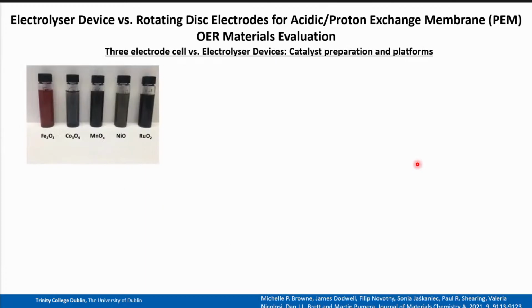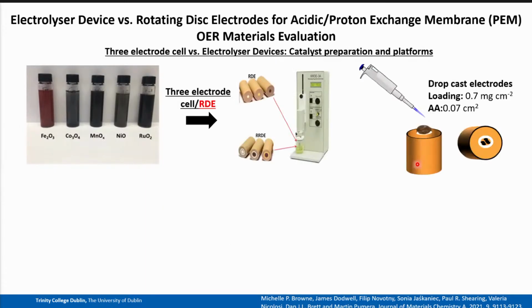So from our catalyst inks, first of all, we made our catalyst electrode preparations for the RDE, or the 3-electrode cell, through drop casting with loadings and active areas, which are very common in literature. So essentially, you drop cast, you let it dry, and then you will push your electrode onto your rotating ring disc, and you will perform your OER catalyst measurements.